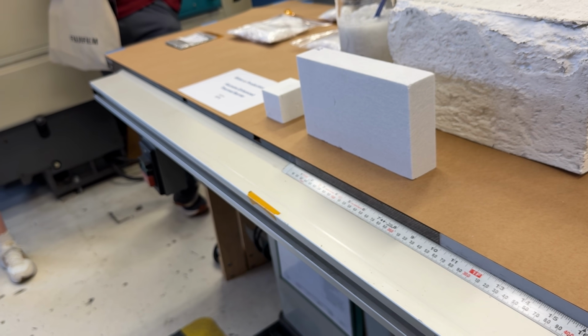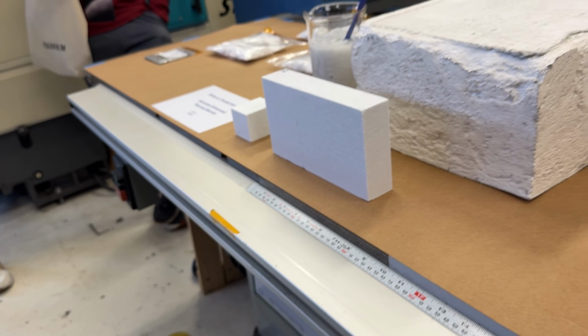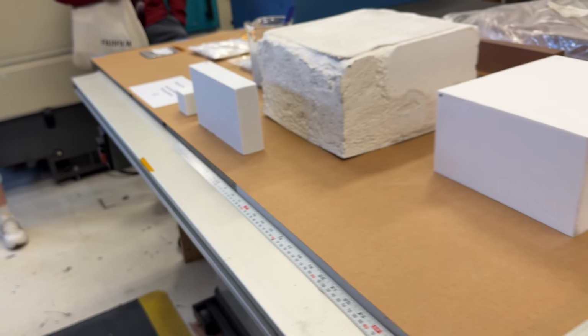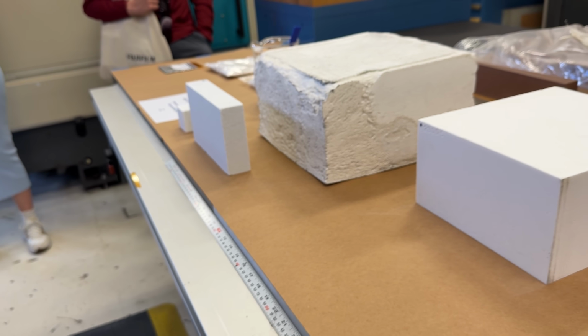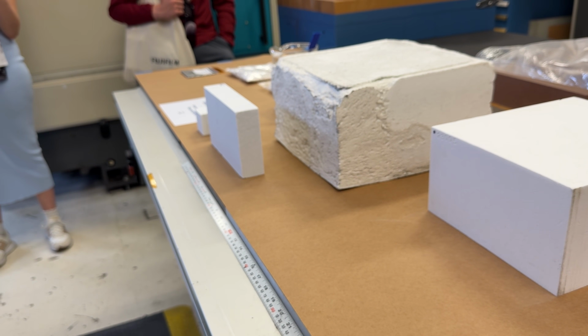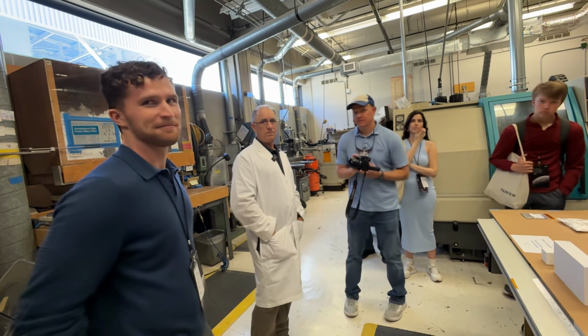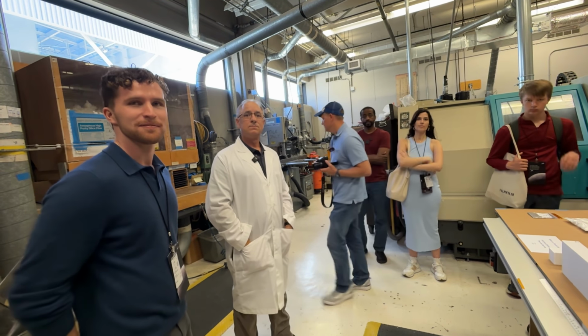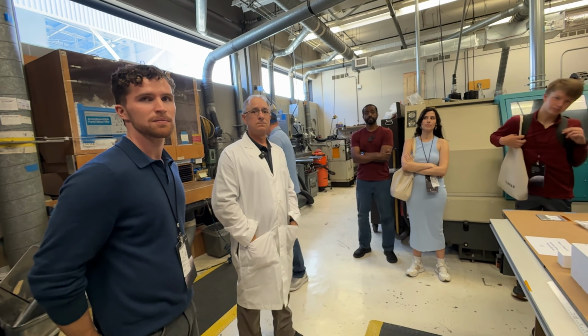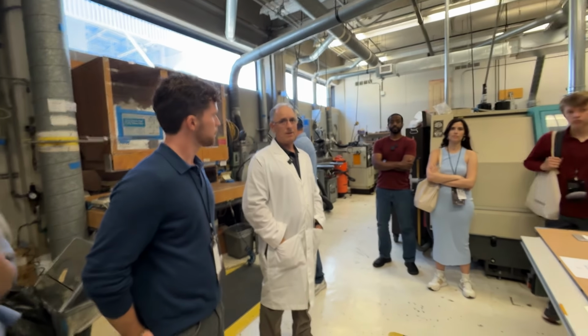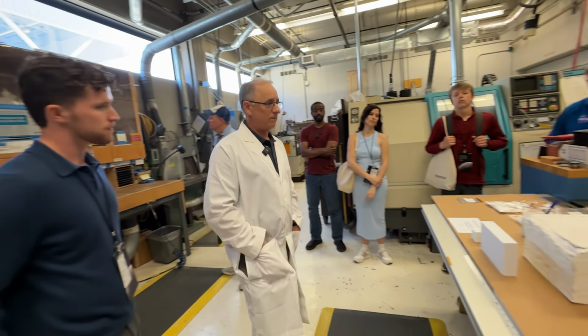If you try to re-enter with this bare tile, you'll get a little bit of the way into your re-entry, and then temperatures are going to increase, and it's just going to melt, and the glass is going to flow like water. For Orion, it's the reverse. The black TPS is on the back shell, and you've got the ablative on the front. So we do have an ablator here.